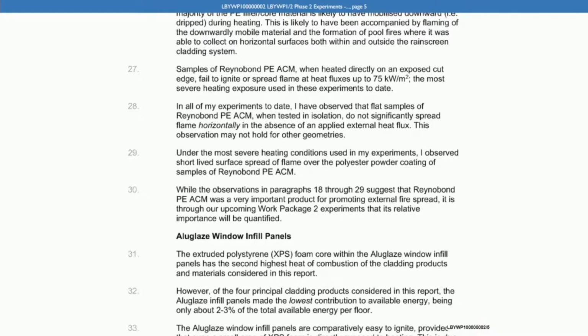I mean, that's a very difficult question to answer. The footage that we assembled at phase 1 didn't show any obvious surface spread of flame over those panels in the early stages of the fire. As the fire grew, it's very hard to say where that spread of flame was occurring, whether it was a consequence of burning of the polyethylene core or a consequence of the powder coat. So, that's a very difficult question to answer. The amount of energy that would be liberated by any burning of the surface coating would be very, very small in comparative terms if you compare it to the amount of energy that can be liberated from the polyethylene core. So I wouldn't think, and I think I intimated as such in my report, that that's a hugely significant observation.